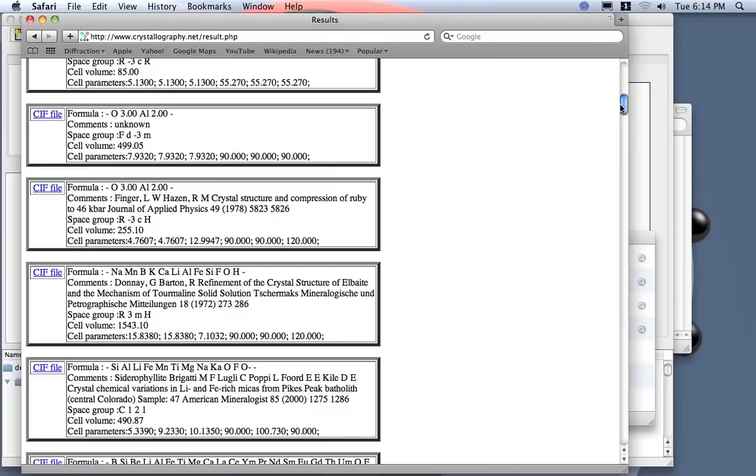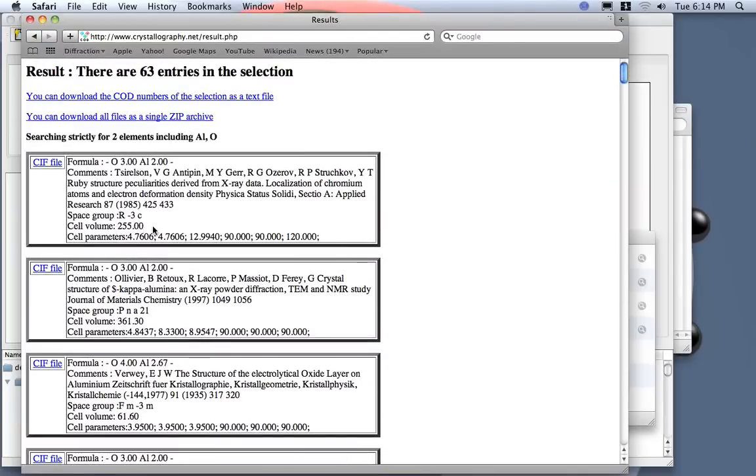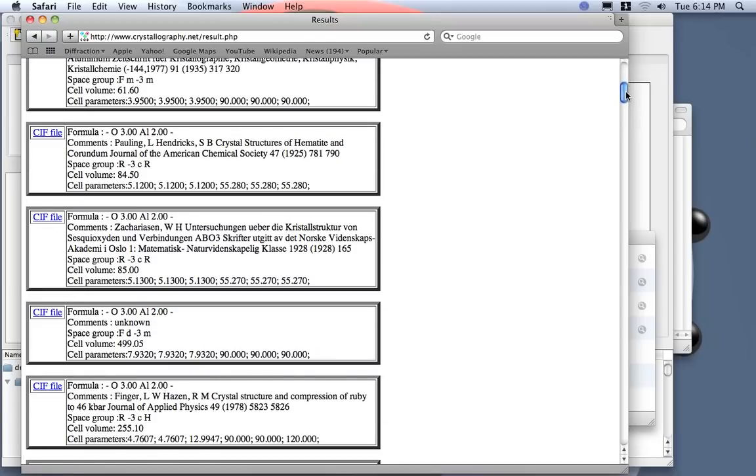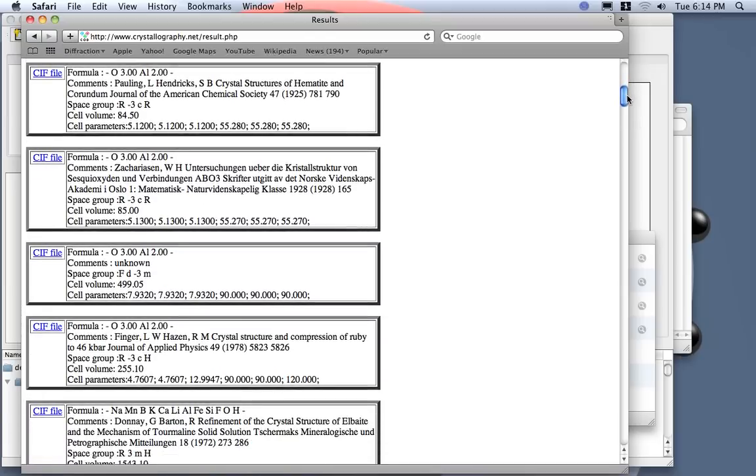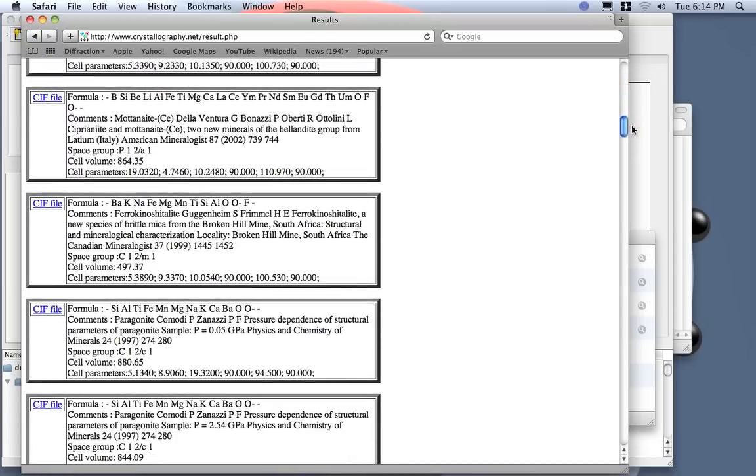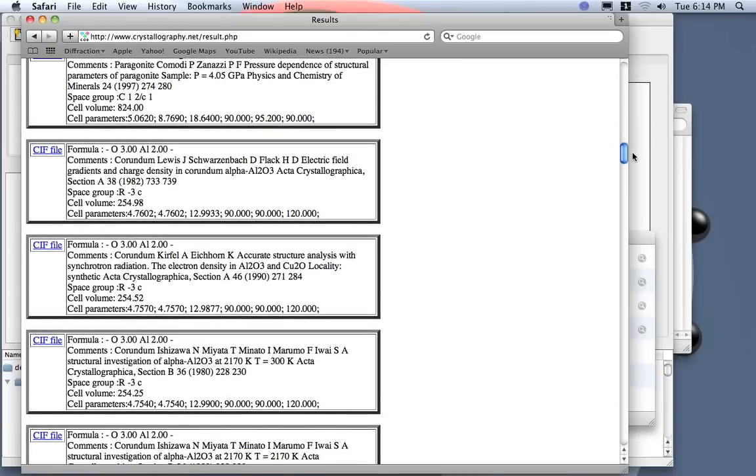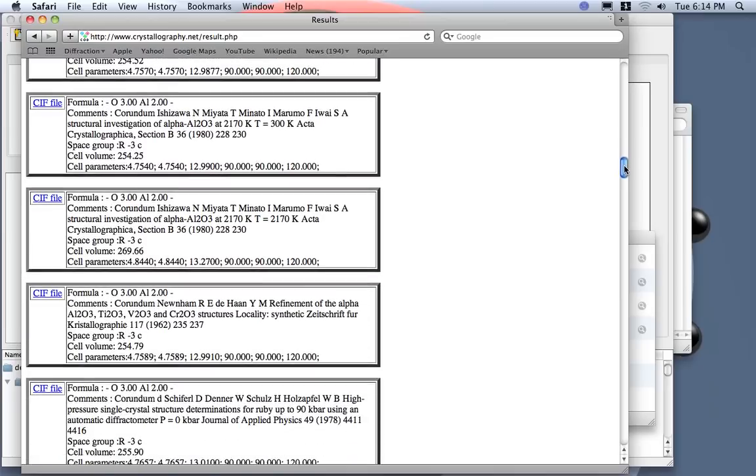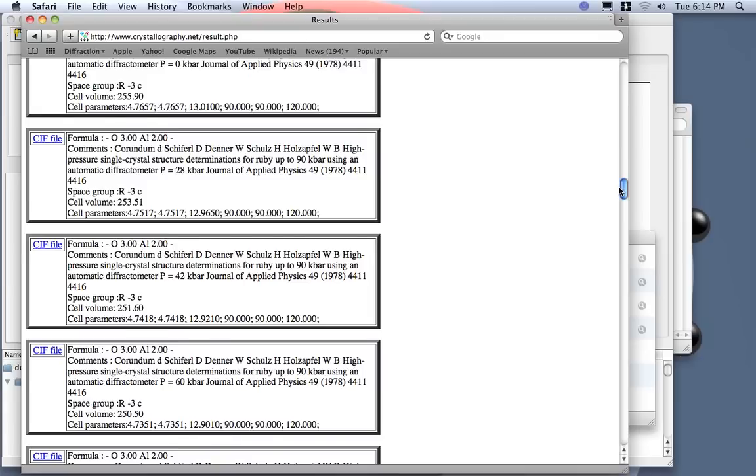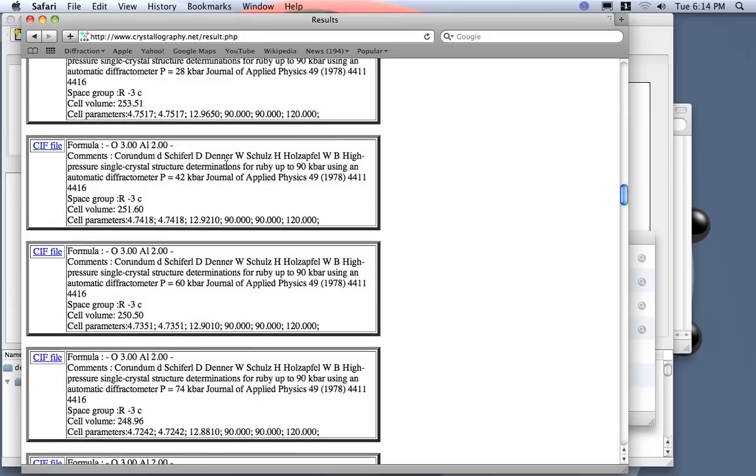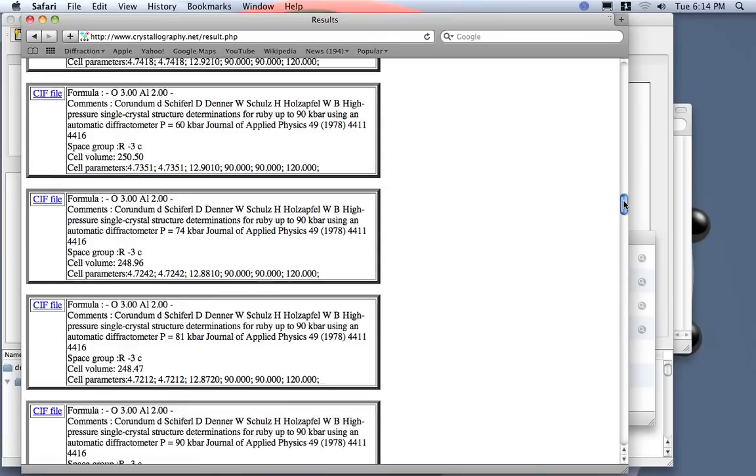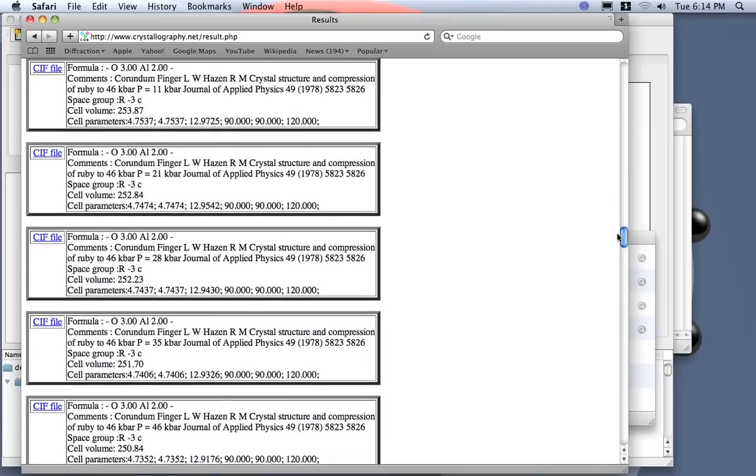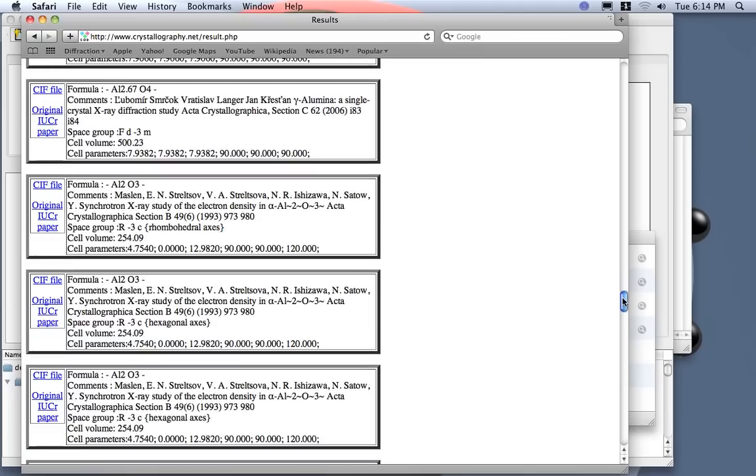Okay, the correct space group for corundum is just the trigonal one. So here, for example, we have one of these. You should look also better to get one best publication. So you may search, and I normally prefer if they are in Acta Crystallographica, for example. If they are done by neutron or single crystal. You should avoid all these at high pressure, because maybe it's not your phase, unless you are looking for a high pressure phase.